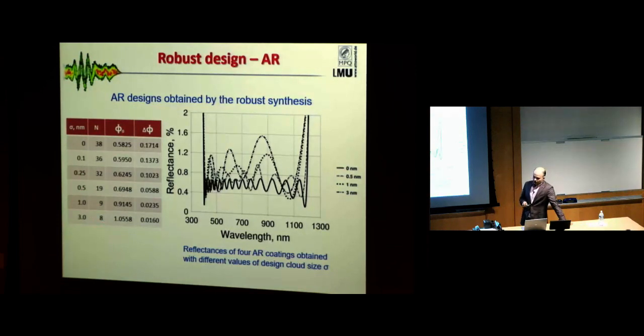And when we apply our robust algorithm, it's quite different from what we have in the case of the standard algorithm. Usually, the design provides you more and more layers, going to infinity with the number of layers. Each step provides a more complicated structure. But as soon as you introduce the precision of your deposition process, this algorithm starts stopping. It's limiting itself.